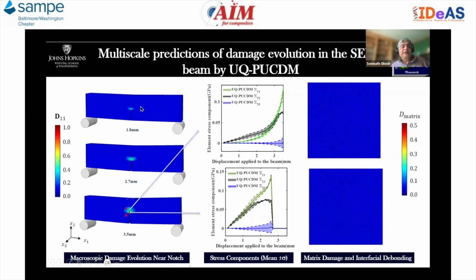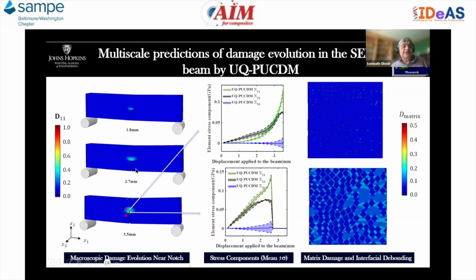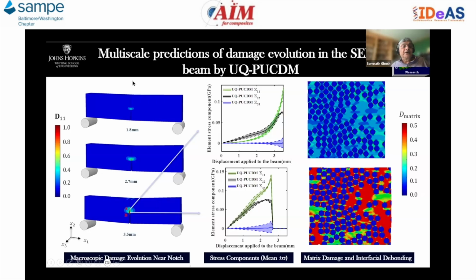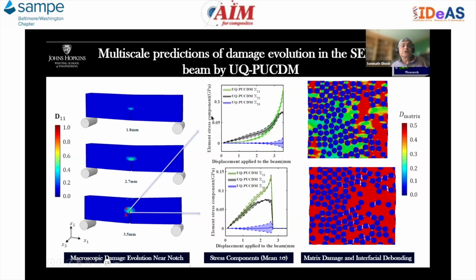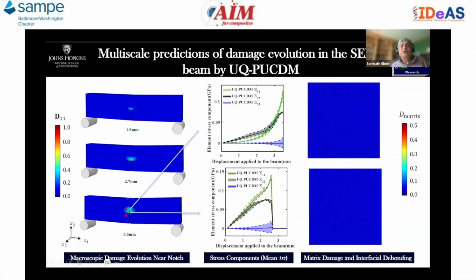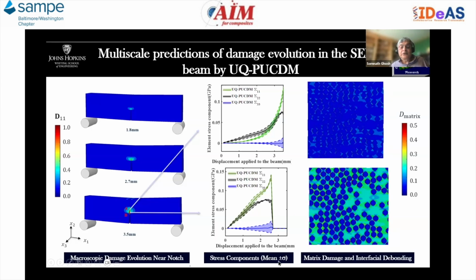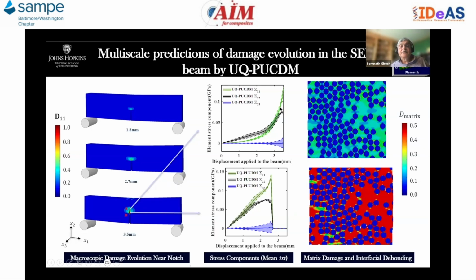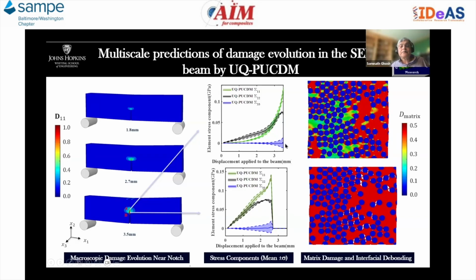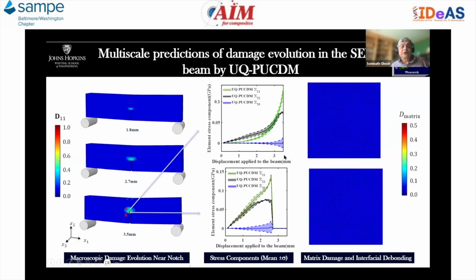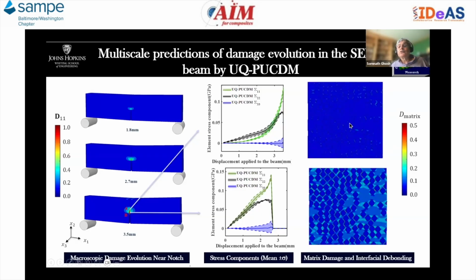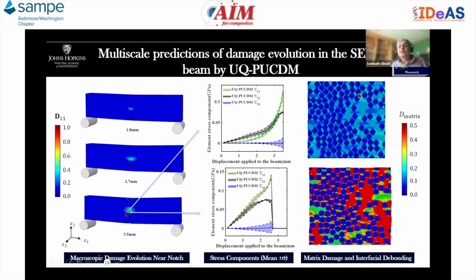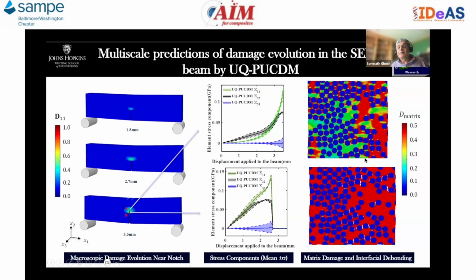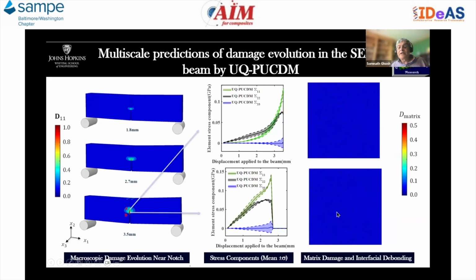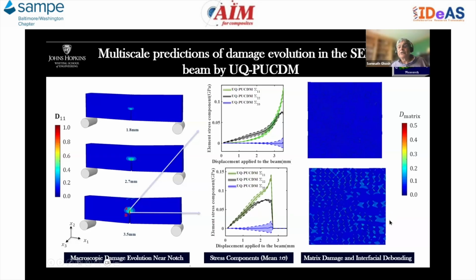You can see on the left side is the evolution of the crack with loading. This corresponds to the element stress component, together with the stress component for the mean plus minus the variance that you are seeing for the different stress components. And this corresponds to the underlying microstructural damage evolution, the matrix damage as well as the interfacial debonding.